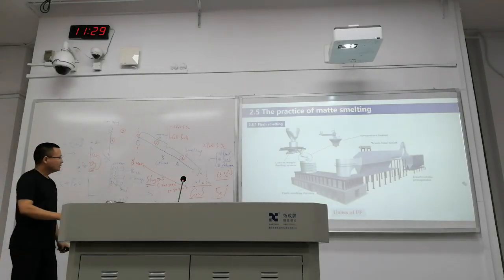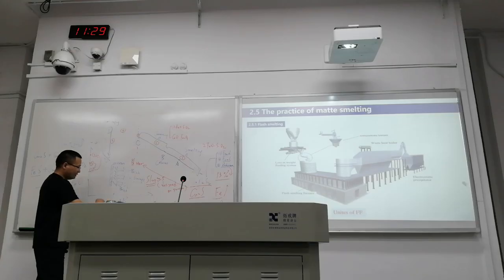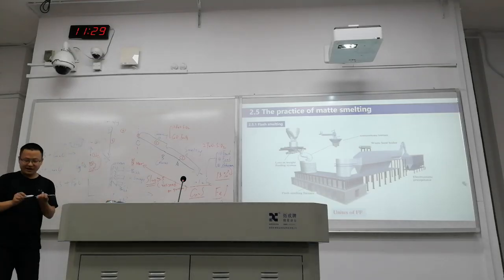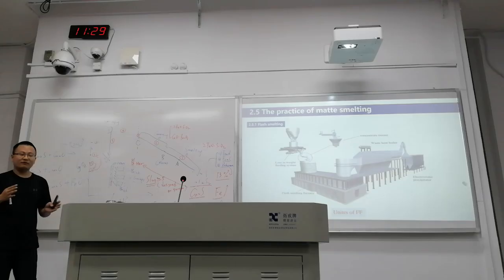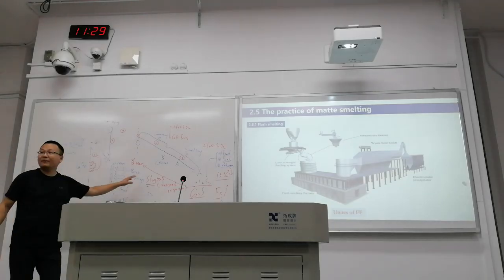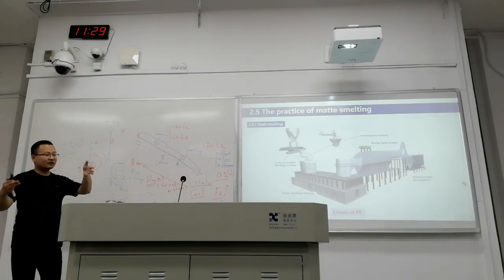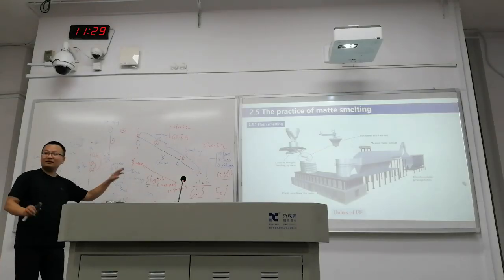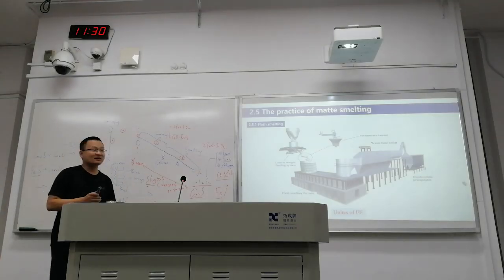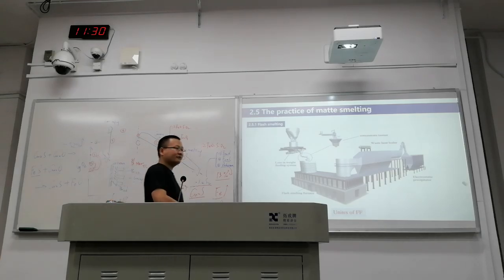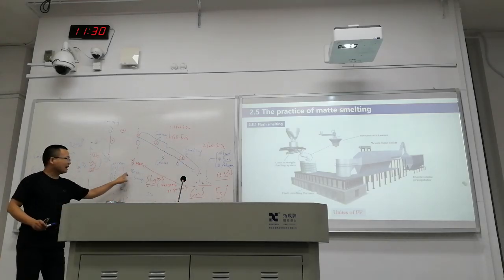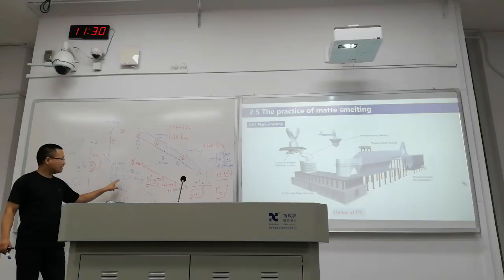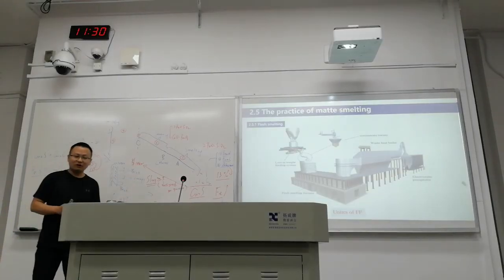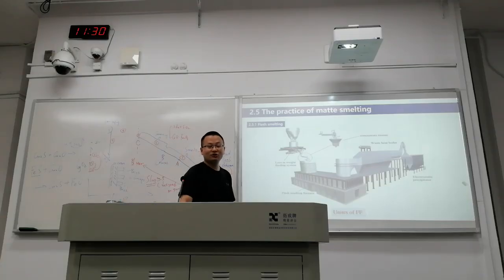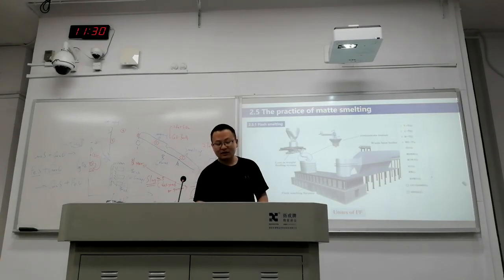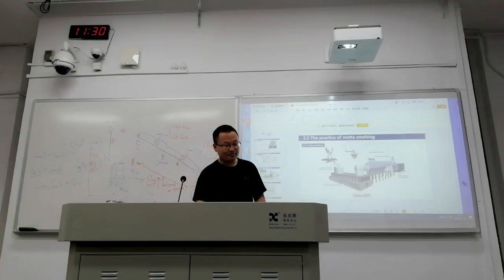So what is more important? It will be the temperature in these bricks, right? So the temperature is well controlled. The lining will be stable. So the dissolving and the forming will be dynamically constant. So actually, if this one breaks, this is oxide, it will dissolve into the slag, and this is the water inside. So if water is linked to the melting phase, it's going to be another very serious accident.